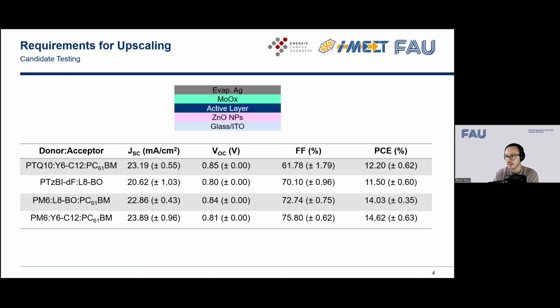One of the classic materials as of now for upscaling is PTQ10. It is often used in combination with Y6-C12, whatever you want to call it. But in this screening, it showed poor fill factors, specifically compared to all the other competitors that we have. It already gets better with the next candidate that uses L8BO as a non-fullerene acceptor. However, here it really lacks in current density, and also the VOC is a lot lower compared to the PTQ10 Y12. However, the fill factor is a lot higher.